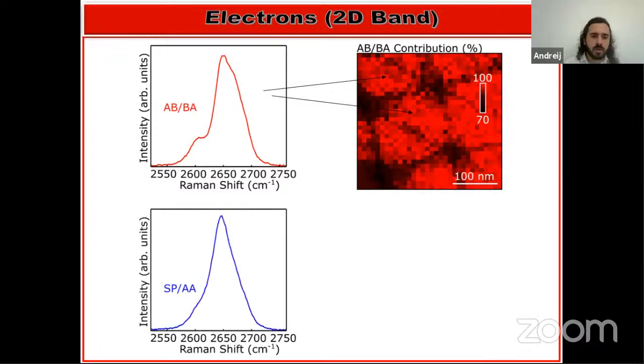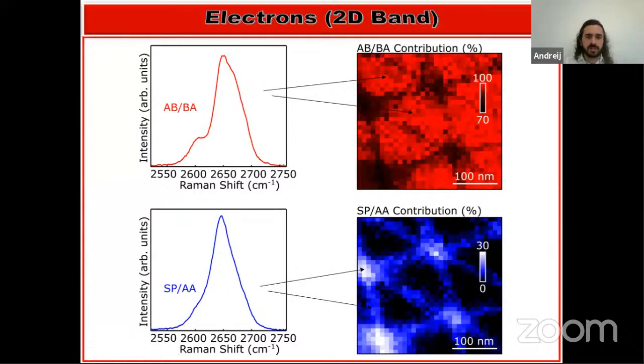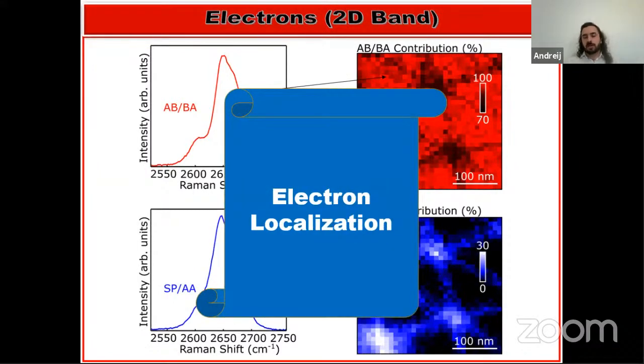And what we saw new here was the spectrum measured at the SP and AA region. And look, it is very different from the previous one. I have never seen this kind of shape before. And when we use this spectrum to map the space, we observe stronger intensities at the AA and SP points, as expected. So these results tell me that the shape of the 2D band varies through the space. So we can say that we observe electron localization, so the electronic structure is varying through the space.